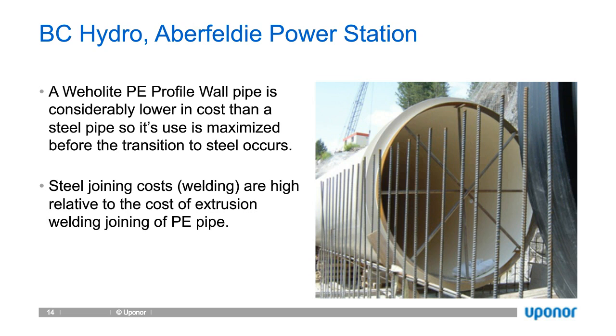So with polyethylene at the joint, the polyethylene extrudate just softens. There is no change of state. Only about a half millimeter or so of the parent pipe material needs to soften to be fully mixed with the extrudate material that we deposit in the joint area in order to form the bond.